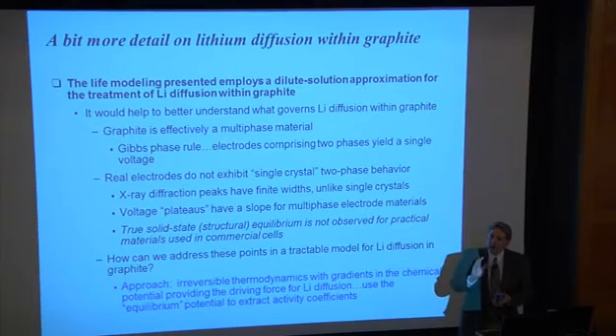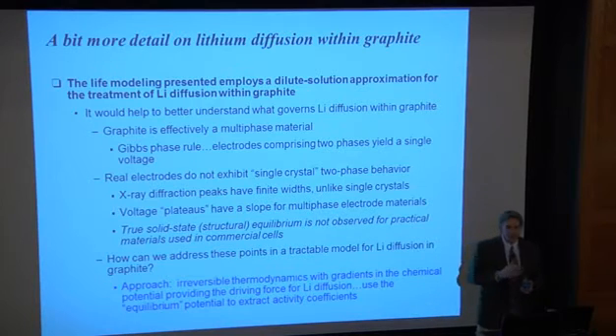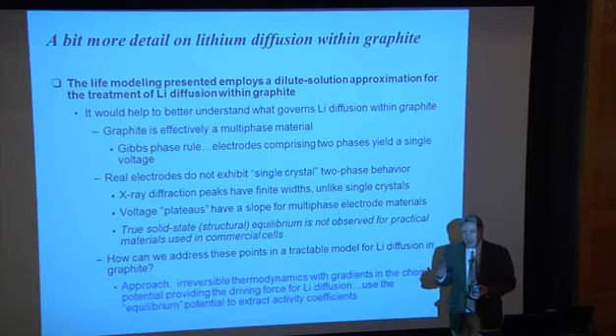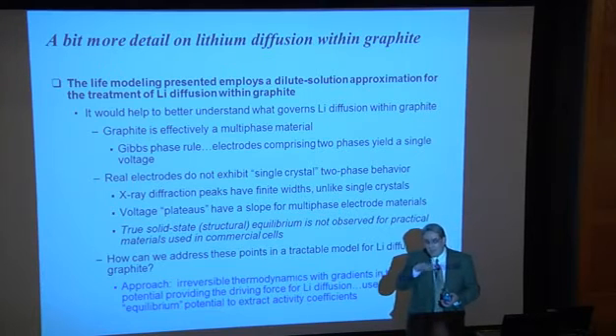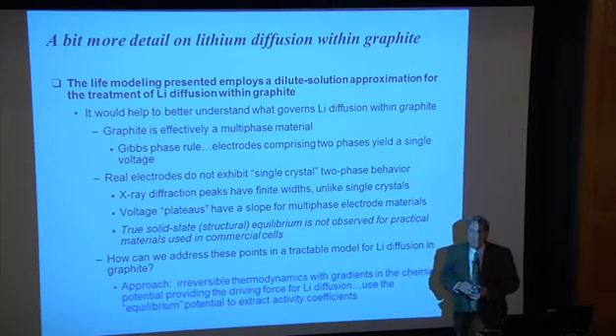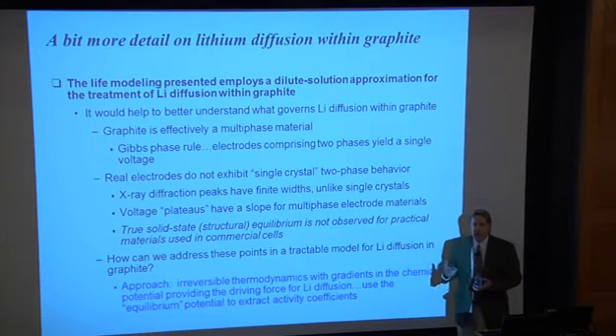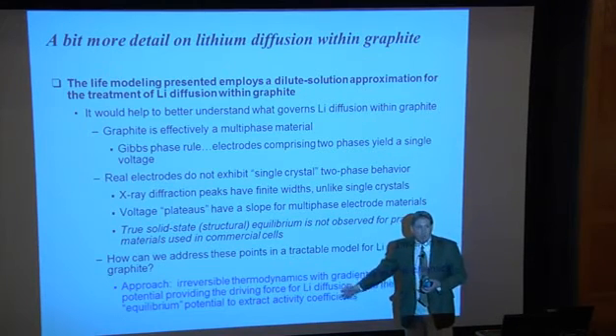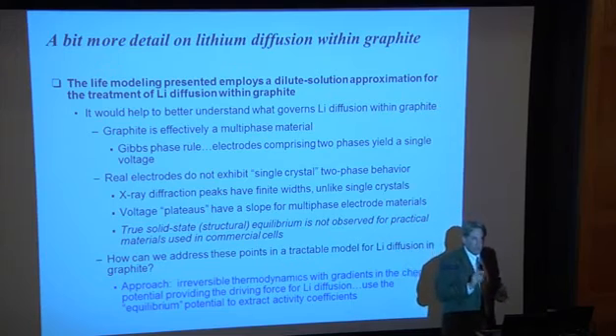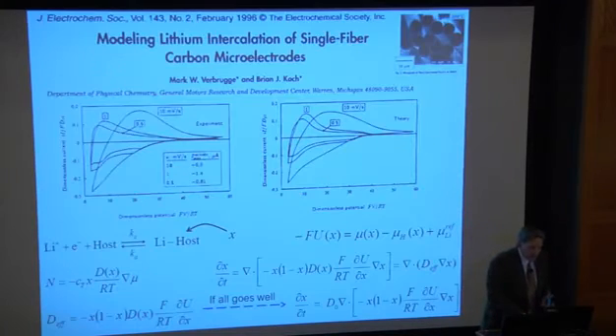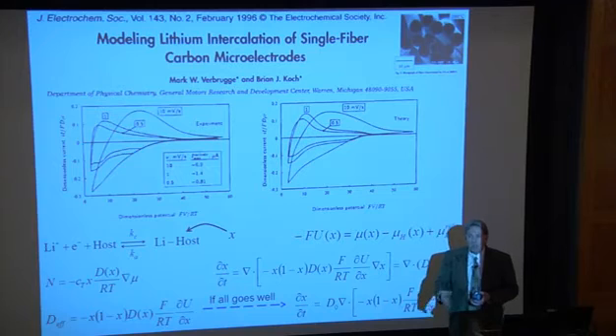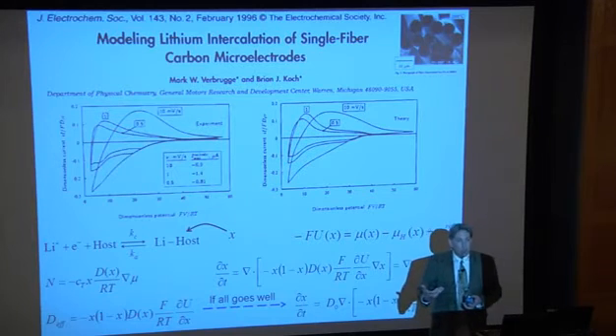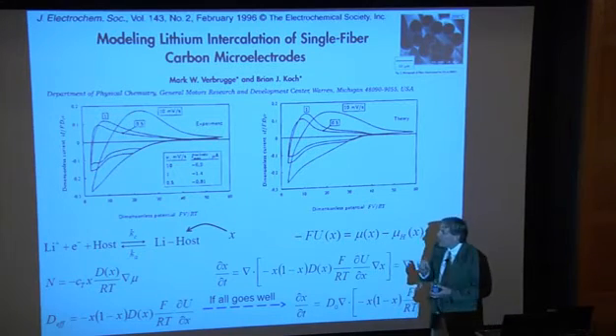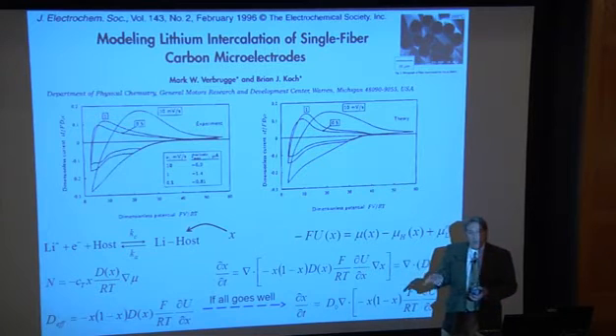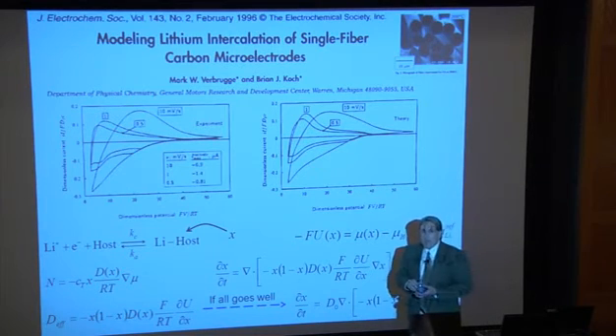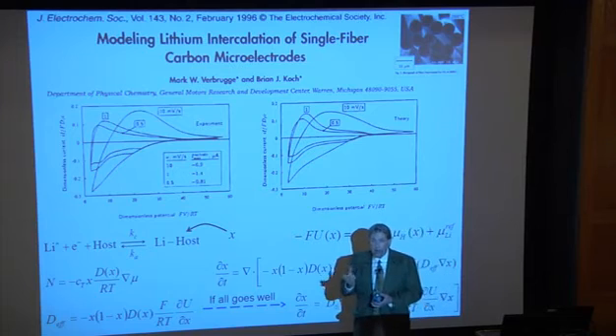But the fact of the matter is, we never have perfect graphite in our cells. And after we cycle them for a while, we get all kinds of dislocations, and you never see perfect 2-phase behavior. There's always some slope when you look at these systems. So my thought was, let's take advantage of this fact that it's somewhat disordered, it's not perfectly crystalline, and let's try to treat it as a pseudo single-phase material. And what that means is to use irreversible thermodynamics on a single-phase material, and I hope this will become more clear. So I'm going to take one digression. When I first went down this path, it was for disordered carbons, and so there you don't have this argument.